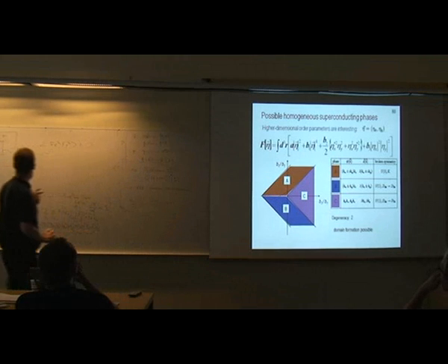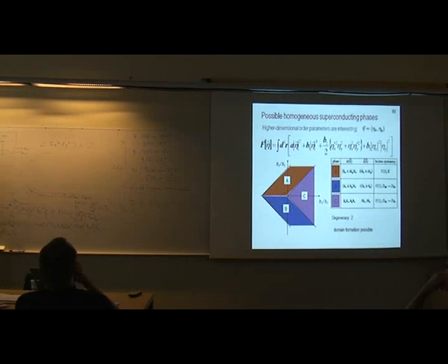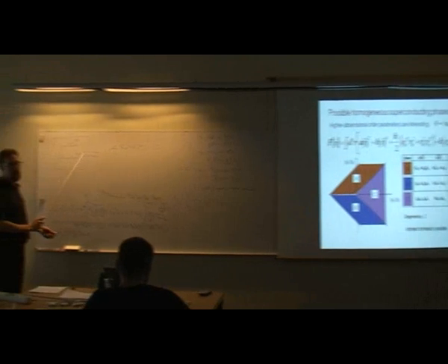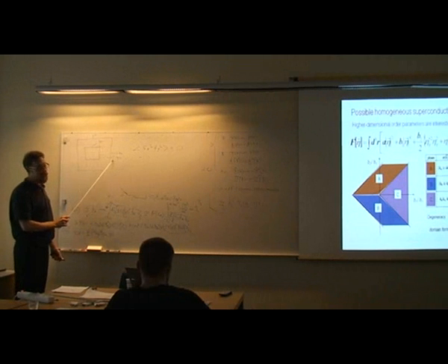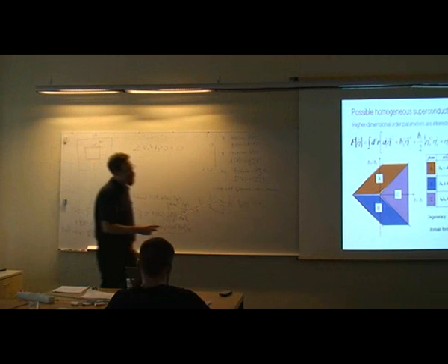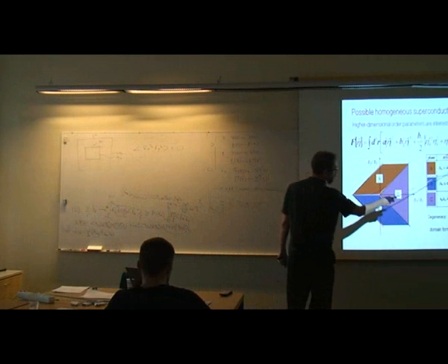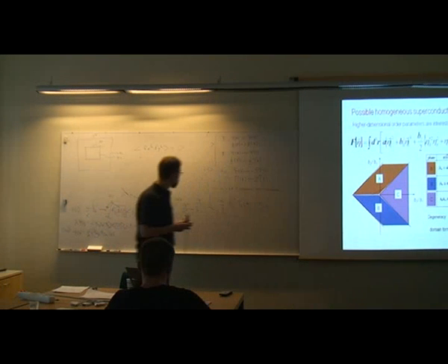So for this particular Fermi surface, you can get a degeneracy between the 1,i state and the 1,1 state. And in fact, you can see that, right? In this picture here, the only way you can get this is if you have two uncoupled systems, ones which run one-dimensionally in this direction, and ones which run one-dimensionally in this direction, and there's nothing to couple their phases. And so there's no reason for the relative phase between delta x and delta y to be determined. And so the fact that there's an i here doesn't matter in that particular case.